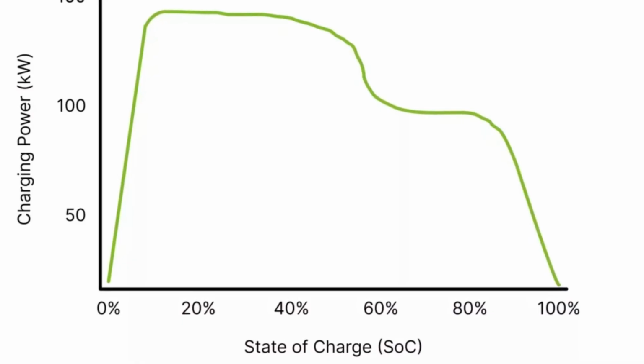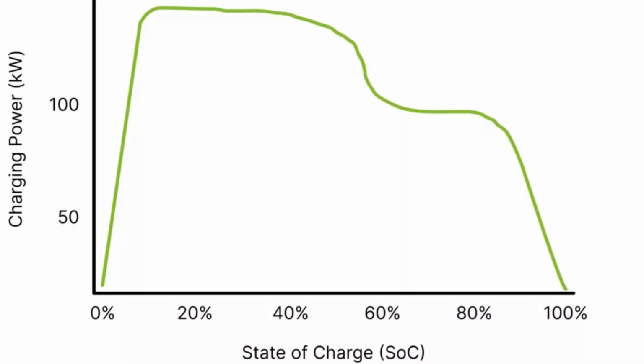From an engineering point of view, the symptoms are familiar. At minus 10 degrees Celsius, an average EV can lose 20 to 40% of usable range depending on driving style and cabin heating. At minus 20 degrees, that loss grows and charging times stretch, sometimes doubling. The charge curve itself changes. Instead of being able to accept high power at low state of charge, the pack limits current early. That protection keeps lithium from plating but leaves the driver waiting and frustrated.